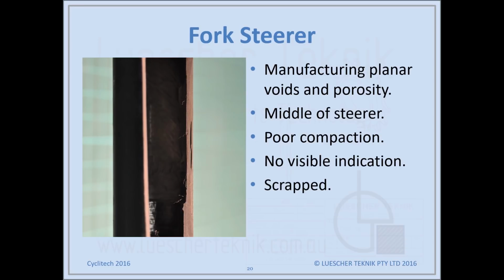So here we have a fork steerer, and you can see quite a large planar void in this area through here, in the middle of the steerer. It's a result of poor compaction; basically the pressure hasn't consolidated the laminate sufficiently in that area. Now there's no visible indication of that on the surface, and due to the area of the void and the location being approximately midway between the bearings, it's a high bending load area. So in this case, it was scrapped.